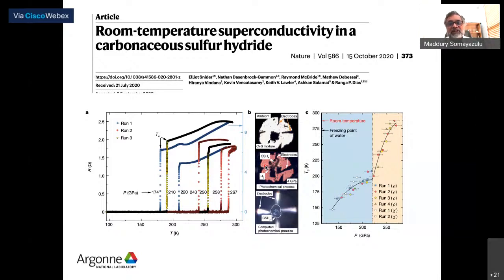And this work showed that you can actually increase the transition temperature with increasing pressure, albeit, of course, there is a little bit of a gap in our understanding of what actually is the constituent of this system. We know it is carbon, sulfur, hydrogen, and it is a hydrogen sulfide dominant system, but we don't really know what the carbon content of that is. There have been more recent papers which have talked about what the structure is, but they're all indirect assumptions or indirect systematics obtained from just the volume points.